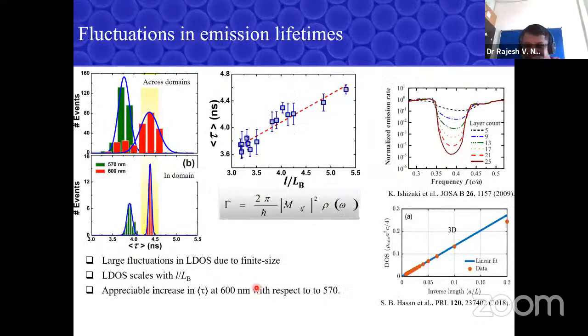Similar to the intensity measurements, we measured again from many domains. You can see there is a huge fluctuation in the lifetimes because of the variable thickness of the sample. If you go with a single domain, you can see a clear distinction between the lifetime measured at the band gap and outside the band gap. So there is a clear increase in lifetime. And if you look at the lifetime as a function of normalized thickness, it indeed shows a scaling. This was one of the great results. When we were doing this experiment, there was a theoretical report in PRL where they showed the density scales linearly with the system size.